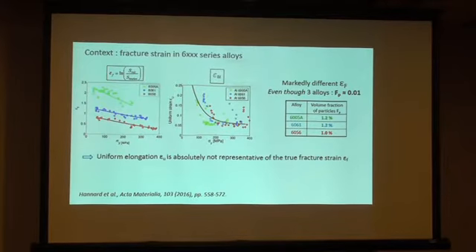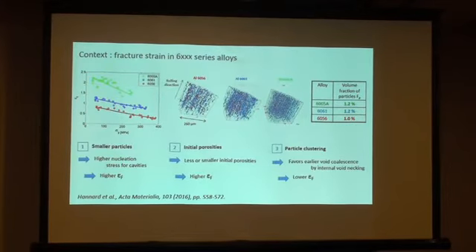So we thought that these differences should come from the heterogeneities of the particle distribution. And in this paper, we developed a model with which we came to the conclusion that these differences can be explained mainly by three key elements. The first one is the size of the particles. If you have smaller particles, the probability to find a defect within the particle decreases, and the stress for nucleation goes higher, and so you get a bigger ductility.